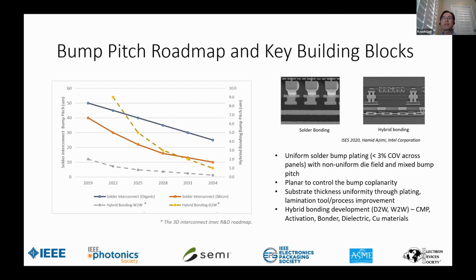And in terms of hybrid bonding, it has been in the industry for a long time, especially starting from the older CMOS image sensor. Now the industry is starting to adopt it in CPU and AI. I still see significant challenges, especially in die-to-wafer configurations, since this needs to deal with additional foreign material and variations coming from singulation, and so on. But ultimately, I believe this is the way you can scale the bump pitch below 10 or to sub-micrometer bump pitch.